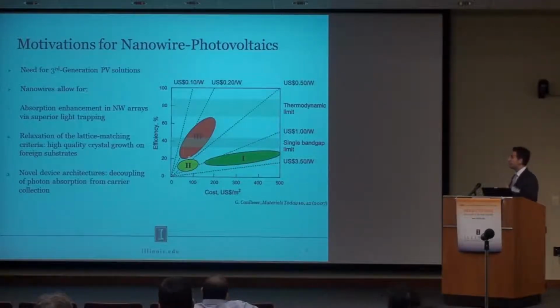So a better solution would be to move towards second generation applications, which are based on thin films, cadmium telluride, organic, CIGS, chalcogenides, and this allows for a significant cost reduction, but it's also associated with a decrease in conversion efficiency. But that's okay because the overall dollars to watt ratio is actually reduced. Now, what we aim to do through the use of nanowires is to really get into this third generation regime, that through the use of nanomaterials and novel hybrid structures, we can take advantage of the novel physics that they provide to not only increase our conversion efficiencies beyond the single band gap limit, but also to keep our costs on par with second generation solutions.